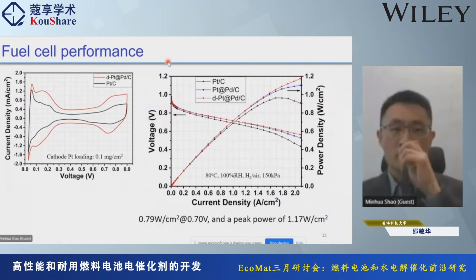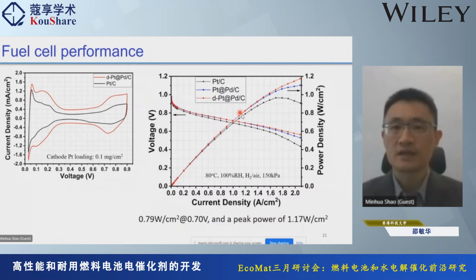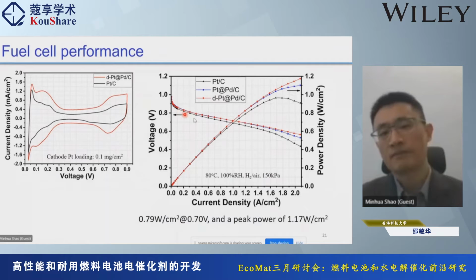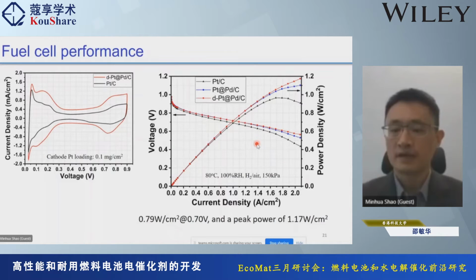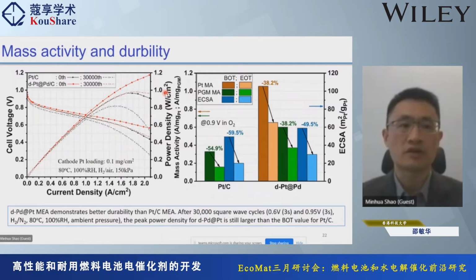All right, so now we also put this catalyst in the fuel cell, and then we tested the performance. We can see that both the core shell with dealloying and without dealloying are much better than the platinum-based catalyst. Okay, but the most important thing here is not only the activity, but also the durability. So we tested the durability of this dealloyed core shell, comparing with benchmark platinum, right? So the red one is our core shell. The black one is the platinum.